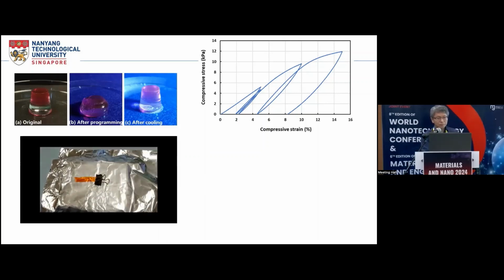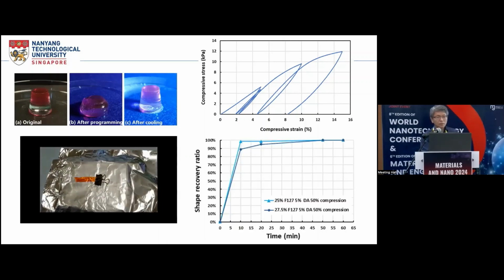Okay, now we have two materials with different composition, and we can see that in terms of recovery, both of them are able to fully recover their original shape in 1 hour. But for one material, this one, within 10 minutes, it's almost fully recovered its original shape, but the other recovers less.